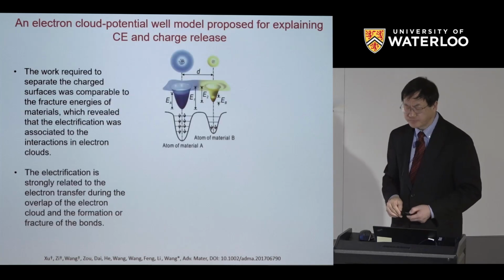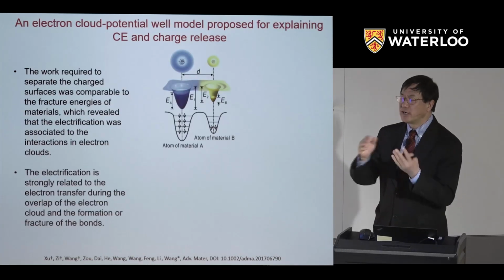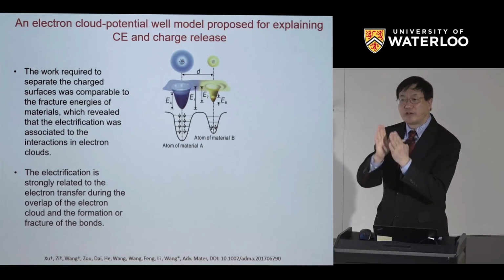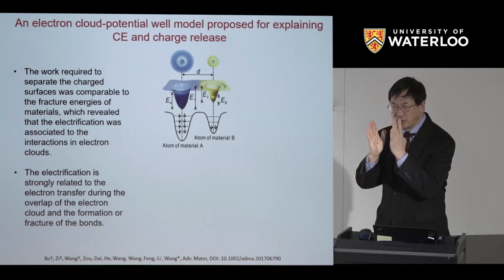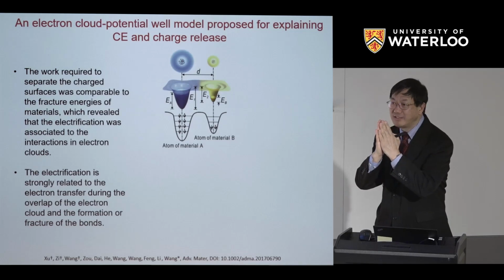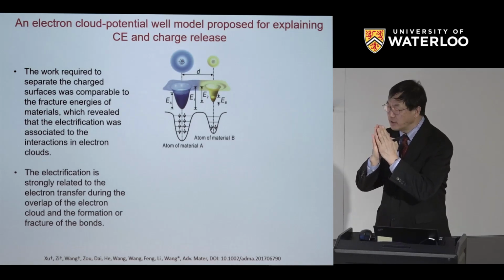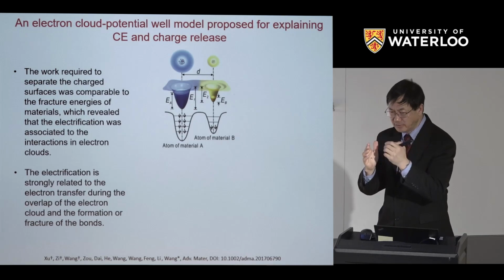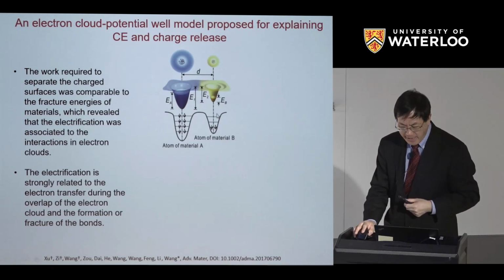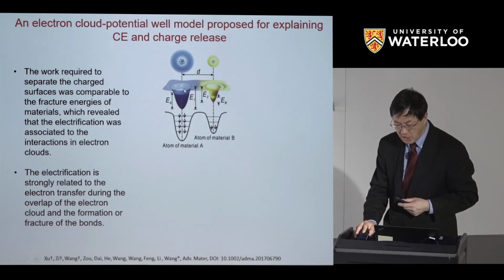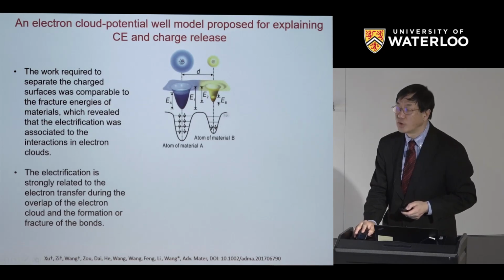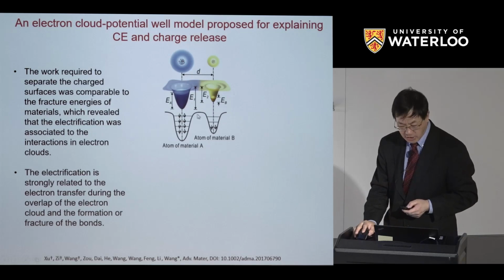So we came up with a model. The way that we see contact electrification, there has to be contact. Why contact? This material has to squeeze the other material. If you look at the atomic scale, that means one atom belonging to material A has to push against the other atom belonging to material B. If they are separated apart, this is the potential well. No electron transfer, because in order for an electron to transfer, it has to overcome the barrier to get here, and the distance is too far. They cannot do that.